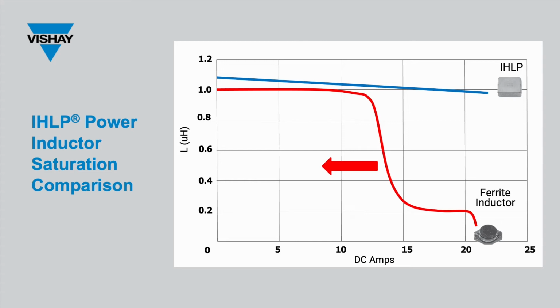Furthermore, a ferrite inductor is very sensitive to temperature. As the operating temperature increases, that same red curve will shift to the left and continue to do so as long as the temperature keeps increasing. The result is an even lower current saturation point, which typically results in a larger, more expensive inductor to prevent saturation at the worst case conditions.